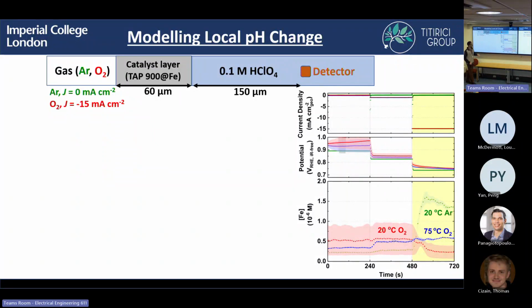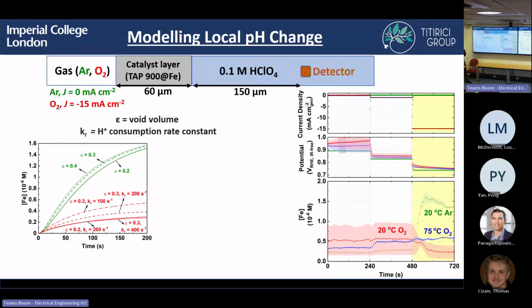And again, just to show you, this is the initial gas diffusion electrode measurements. And I've just converted here, this is iron concentration in 10 to the minus 6 molar. But it's still the same values as before. And so Antoine developed this model, and he tried to semi-quantitatively replicate what we saw in the measurements. So you can see here, this is the iron concentration over time, where we see, in this case, he developed it based on the argon measurement.